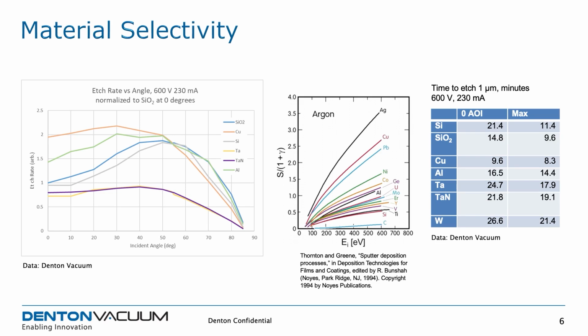In this case, when you have an ion beam, the material selectivity, even if you're comparing something like a refractory metal like tungsten and a very soft material like copper, the difference in etch rates might only be a factor of 2 or 3. In order to get that down to 0 so that we can etch in a planar way from the top of the chip down to the lower metal layers, 1 degree of freedom we have is the incident angle. So this is why it's important that the tool tilts from 0 to 90 degrees.